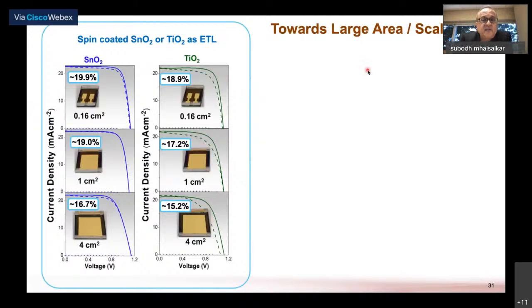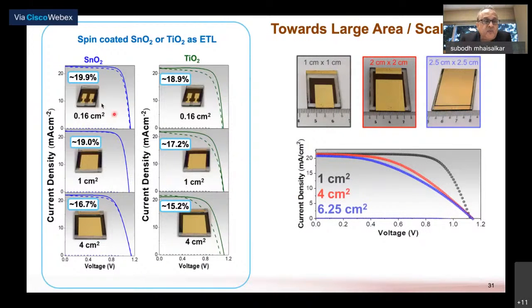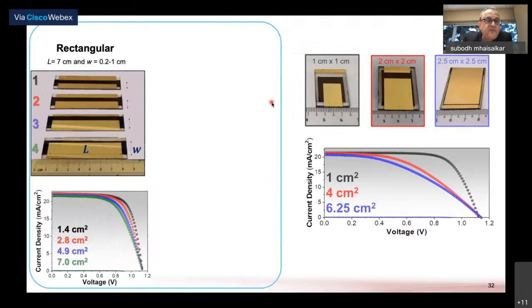Coming back to the discussion in terms of towards large area deposition, I'm showing you the transition from about 0.16 centimeter square to 4 centimeter square. One of the things we noticed as we went larger in size, as you can see from this graph, is that you really do not see very significant differences in terms of the current or the VOCs. What you do see a significant drop in is the fill factor. So we decided to study this factor a little bit more.